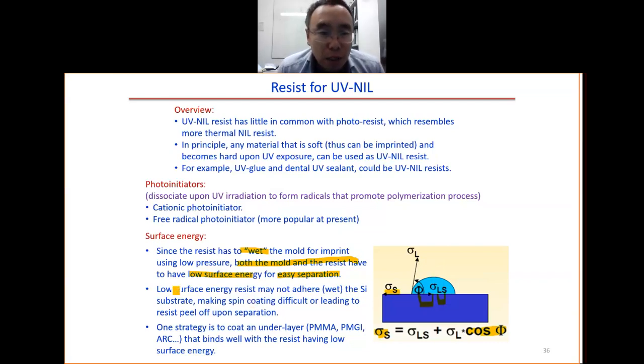One issue is that because we have very low surface energy, spin coating may be difficult, because, as I said, it is kind of hydrophobic. Spin coating may be difficult, and there may also be resist peeling off. If the surface energy is too low, the resist may peel off from the substrate. One way to solve this problem is to have an underlayer, such as PMGI or polydimethylglutarimide, or ARC, anti-reflection coating layers. Those polymer layers are not as smooth as the silicon, and they have a high surface energy. So spin coating will be less of a problem, because the polymers are not as smooth as the silicon.